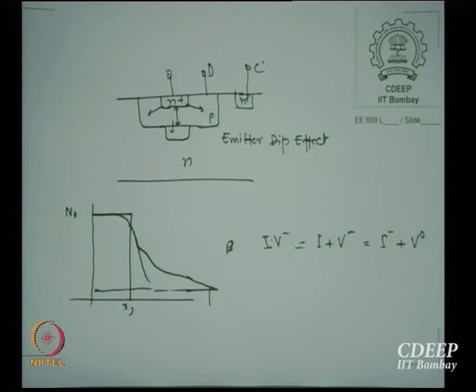You thought it is a 0.1 micron junction, it may become a micron junction. Now this effect has to be known a priori, because otherwise the junction depth, which is deciding the base width or any other parameter, may actually go so awry that the performance of the circuit will never be what you wanted. Therefore, when this anomalous effect was first observed many years ago, people realized that there must be something more to it, and they looked into the physics once again and said, okay, there is an additional diffusivity and breaking down of pairs which causes vacancy creation, which allows excess diffusivity.